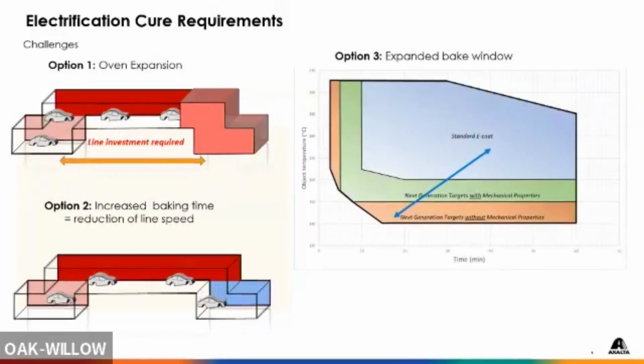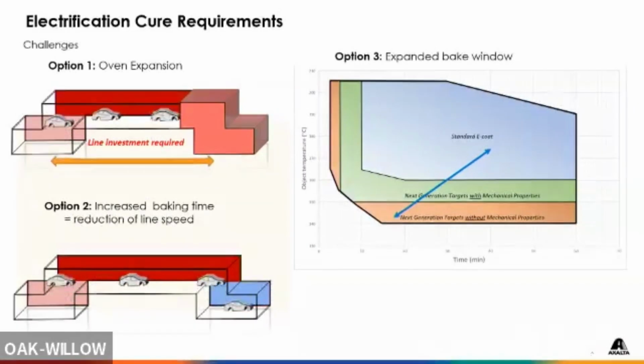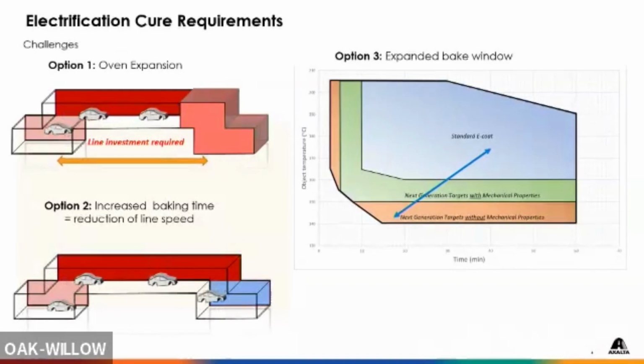So that leaves us with the third option, which is to put it on the paint supplier and make them change the product and make it work with our system. And that's what we did. As you can see, the blue is what we consider to be a standard bake. Again, within the same toolbox, I can move into the green area without a lot of effort. Just, again, changing catalyst level, changing a little bit of the backbone resin, playing around with the polymer architecture, maybe going to a little bit different crosslinker or a blend of crosslinkers. But to get to the orange area, that's a new system. Okay? So those are my three options. Guess which one our customers pick? Number 3, of course.